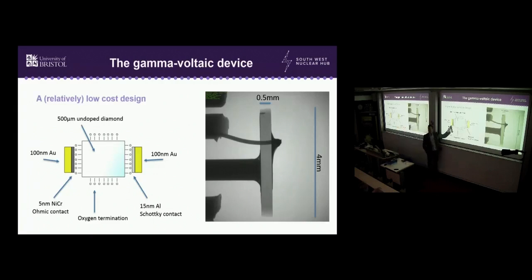So the gamma voltaic device is pretty simple. We have an ohmic contact on one side, which is typically nichrome, and then we have a Schottky contact on the other side, which at the moment our favoured one is aluminium, and then we have gold on the outside of that. So essentially we're making a sandwich, a diamond sandwich, very, very simple. And we're using electronic grade undoped diamond at the moment, but we'll be increasing our boron doping to improve the device. And you can see there's an X-ray, a radiograph, of the diamond gamma voltaic.